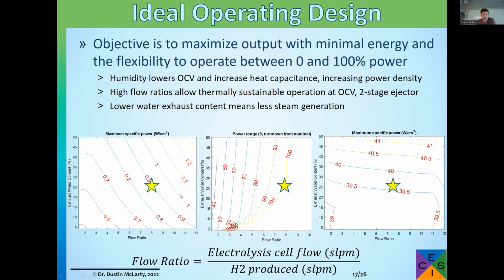So I'm showing here sort of an ideal condition is maybe 25 to 30% exhaust water humidity. And that gives you, if you have a high enough flow ratio, the ability to turn your system all the way down to open circuit voltage and operate at zero power when the sun isn't shining. And through all this, it's fairly efficient. It's under the target 40 kilowatt hours per kilogram. So this would sort of be an ideal way to design your high pressure, high temperature electrolyzer.